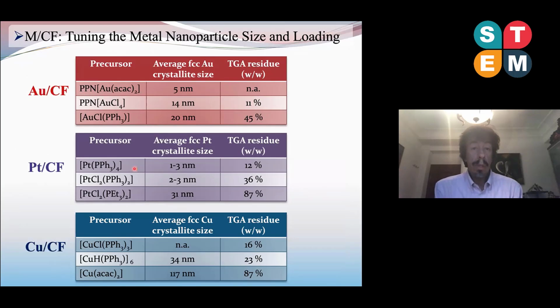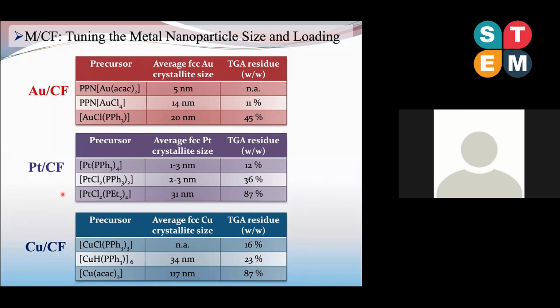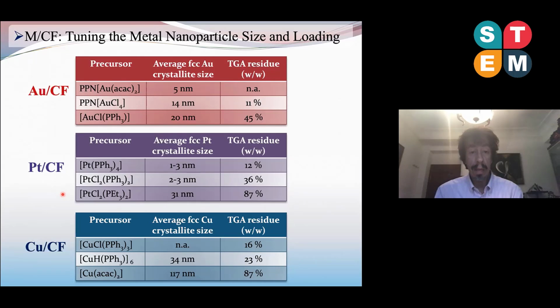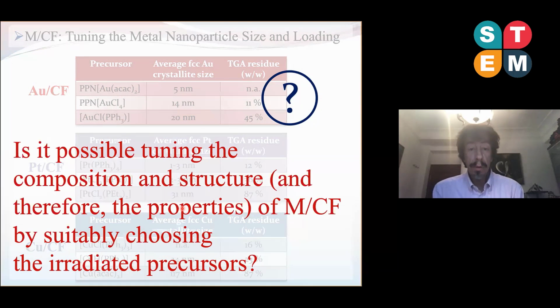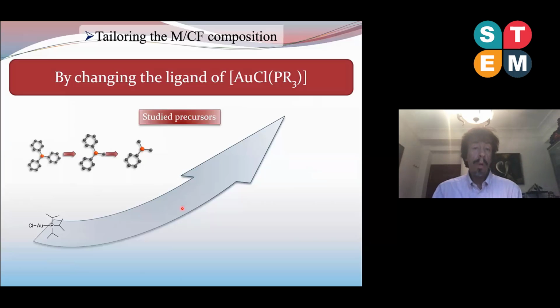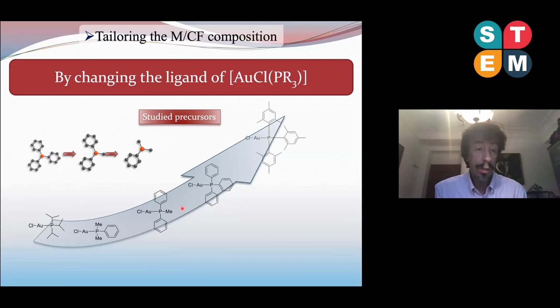So we realized, when we did XRD studies as well as thermogravimetric studies to measure the carbon content, the metal content, and the metal nanoparticle size, that by changing the metal and the ligands, the organic moieties, we can change the particle size and the carbon content of these metal carbon foams. So is it possible to tune the composition and structure, and therefore the properties of the metal carbon foams, by suitably choosing the irradiated precursors? What we did is a systematic study just using different gold phosphines.